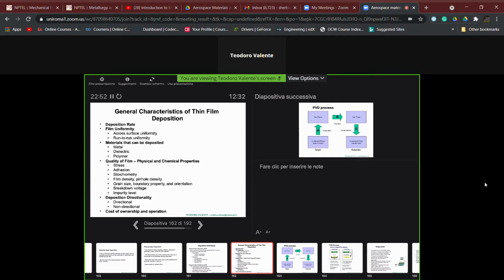For dielectric materials, the so-called breakdown voltage, and in general also the composition, which is related also to the stoichiometry of the film itself, the presence of impurity level. The deposition directionality can be directional or non-directional.